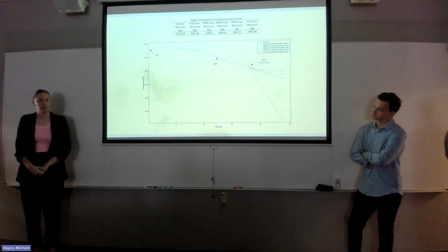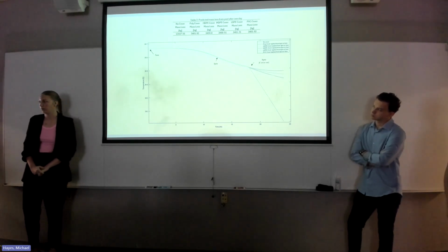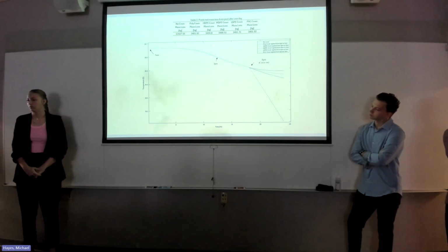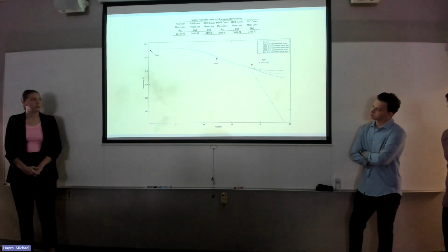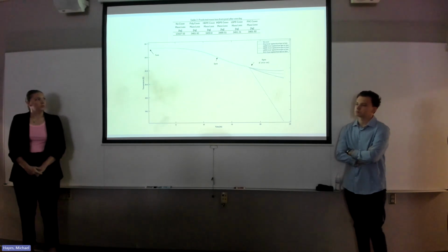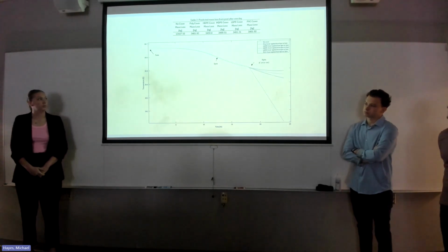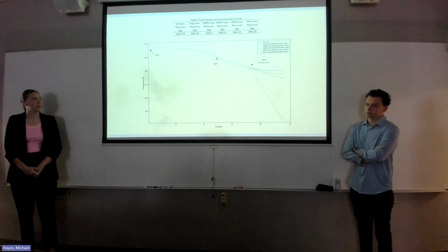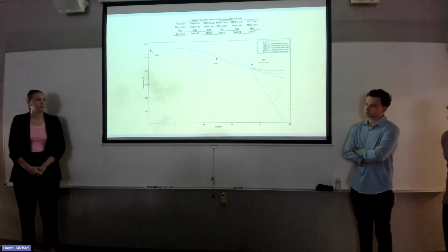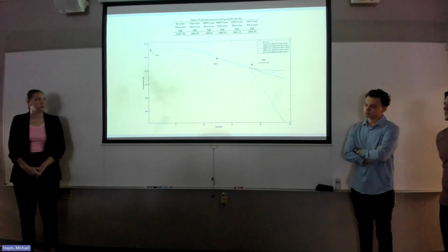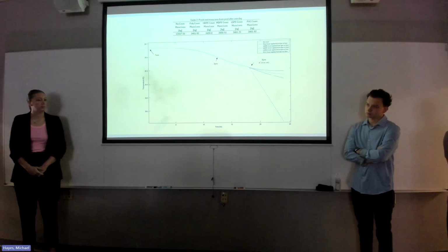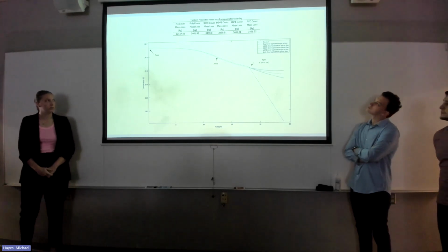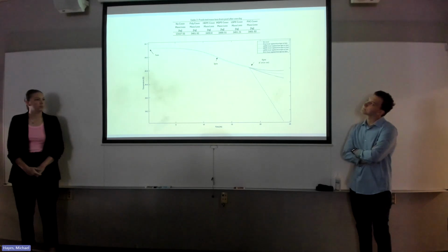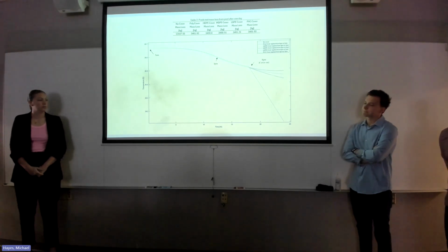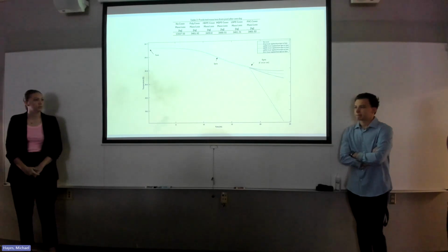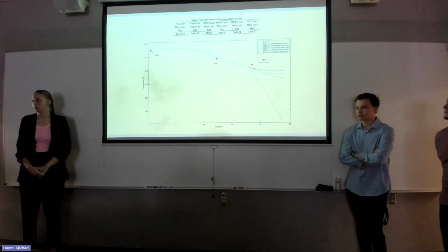As we progress throughout the day, we see minimal losses, but then at 8 p.m., once the sun goes down and you're no longer getting help from that radiation heat transport with no cover, that dashed line really starts to drop down. So this really drives home the importance of having a solar pool cover to help reduce losses. We saw that the best performing covers, the ones able to maintain the pool temperature the best, were the high density polyethylene and medium density polyethylene covers, with the corresponding evaporative losses shown in table 1.